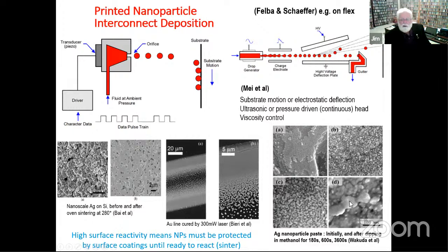The nanoparticles must be protected by a surface coating, because they will react together in whatever container you've got them in, unless they're protected until they're ready to react or to sinter. And here there was a polymer coating on the nanoparticles, and it was dissolved in methanol. And so the whole particles would aggregate together.